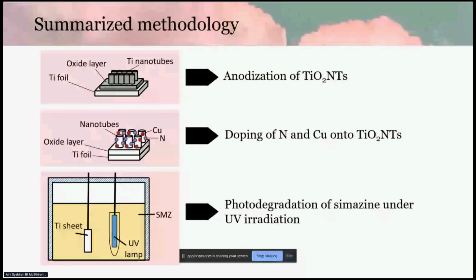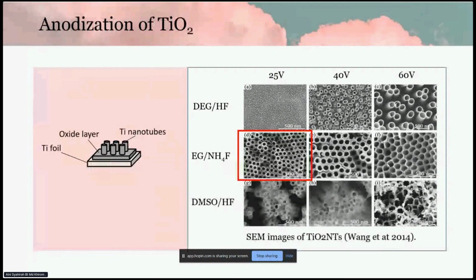So this is the summarized methodology of the project. There are three stages primarily: the anodization, doping, and photodegradation of simazine under UV light irradiation. During anodization, the first stage, an oxide layer will be formed on the titanium foil surface, as you can see in the image on the left. In the presence of fluoride ions, the nanotubes will be formed by forming holes on the oxide layer.